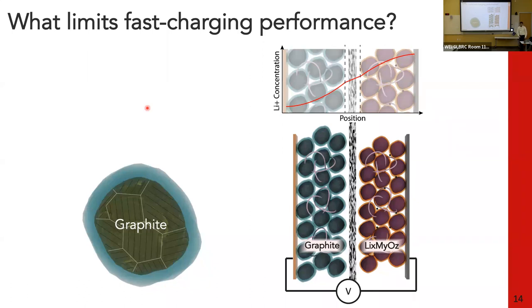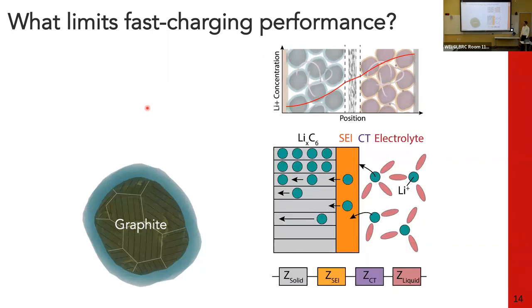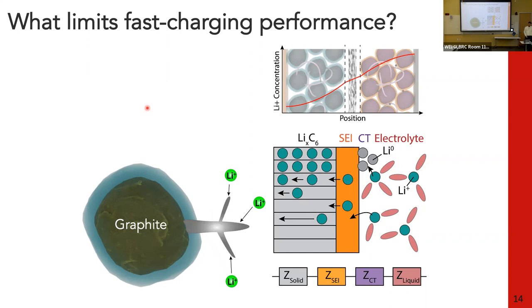And as a result of that, you get current focusing near the surface of the electrode here. So these green circles pile up at the surface of the electrode there. And eventually, they get so unhappy inside of the graphite, all the slots are filled, essentially, you plate out lithium metal, that metallic lithium. And metallic lithium is extremely reactive towards most things, including the liquid electrolyte. So you continue to grow those metallic filaments. You form SEI on the surface of that metallic lithium, which consumes lithium from your active reservoir.